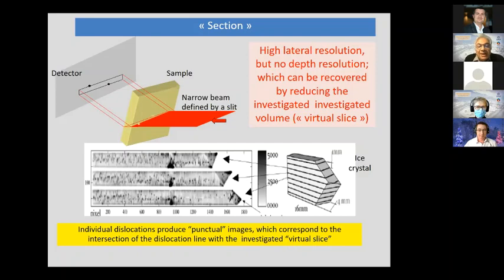Let's talk about another technique we use all the time. It corresponds to the fact that we have a beautiful lateral resolution in the micrometer range, but in depth, as you project 3 dimensions on 2 dimensions, you have a low resolution. You can recover the depth resolution by reducing the investigated volume, by having a narrow beam, say 10 micrometers, and you look, as a first approximation, at a kind of virtual slice.